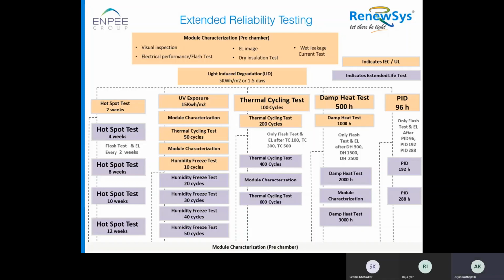The next set of modules go for thermal cycling. As per IEC it is 200 cycles, but we do 600 cycles. After every 200 cycles, it goes for flash test and EL to ensure what the power drop is at different testing conditions. And damp heat, as per IEC, should be 1000 hours. We do 3000 hours. It's basically 3 times the IEC.